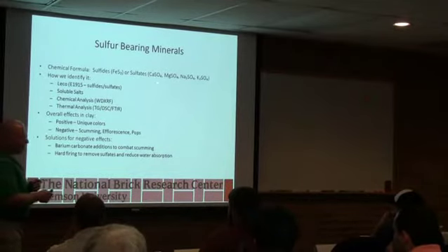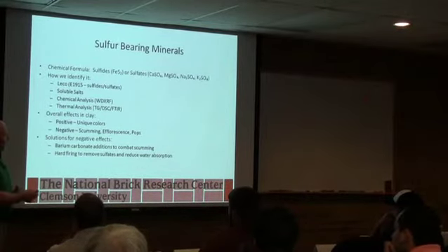It's similar to, do any of you use barium carbonate? Okay, you're using barium carbonate because you have soluble sulfates in your raw material that would normally cause scumming, and you're adding the barium to try to make the soluble salt into an insoluble salt that doesn't move around with water. So to figure out how much barium you need, you need to know how much sulfate you've got, and we can do that with the soluble salt test. The barium people also do a Baridex test. It's similar, just a little different than what we do, but it's all to the same point. So we can use that also to calculate in the raw material how much barium carbonate you need.